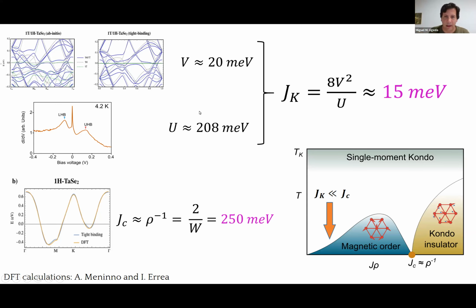over the Coulomb repulsion. And this number can be extracted from the ab initio calculations, which have been fitted using tight binding calculations. So we can extract a hybridization energy of 20 milli-electron volts. The Coulomb repulsion was estimated by the STS results, giving an estimation for the coupling strength of 15 milli-electron volts.